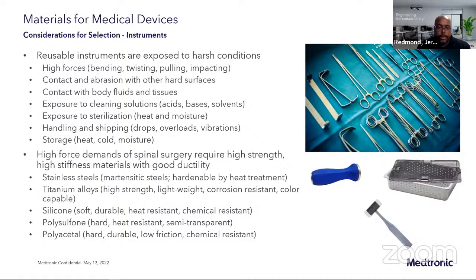Titanium alloys are used in some instances, and one of the real benefits of titanium is that its stiffness is quite a bit lower than stainless steels or cobalt alloys, but the material can be processed to really good strength. So you can get a high strength material, it's lower stiffness, it's a lightweight material in terms of its density, and so you can get something that can be easily manipulated and handled.